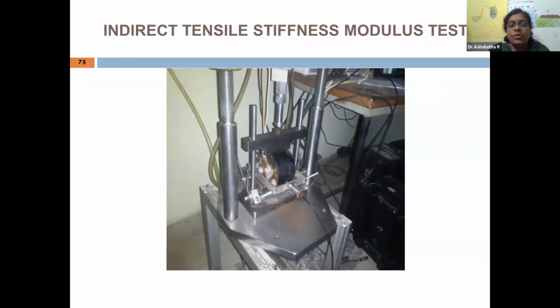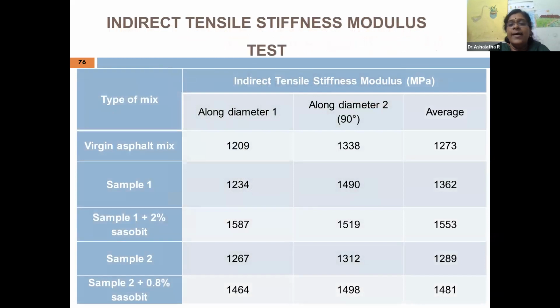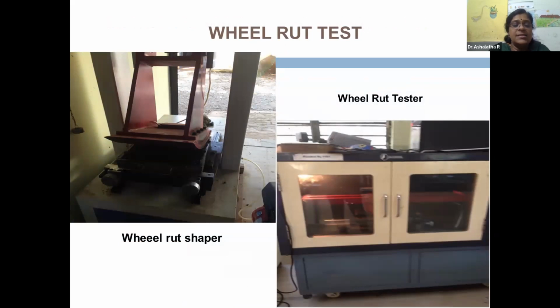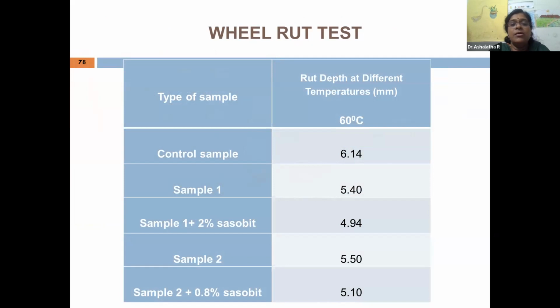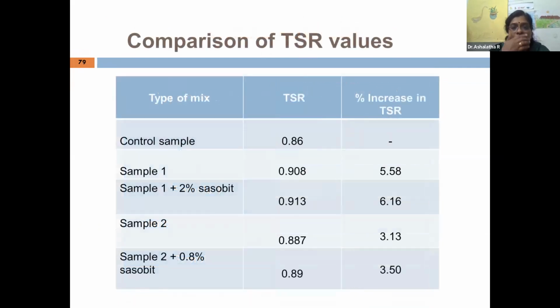And this is the indirect tensile stiffness modulus test. These are the values for virgin asphalt mix, sample 1, sample 1 with 2% Sasobit, and with 0.8% Sasobit, and these were the average values which were reported. We also conducted a wheel rut test, and these are the results of that, at 60 degrees centigrade. For the control sample, the rut depth was 6.14 mm, and the test was conducted on all the samples. TSR values were also compared for all the 5 cases, and the percentage increase in TSR was also worked out.